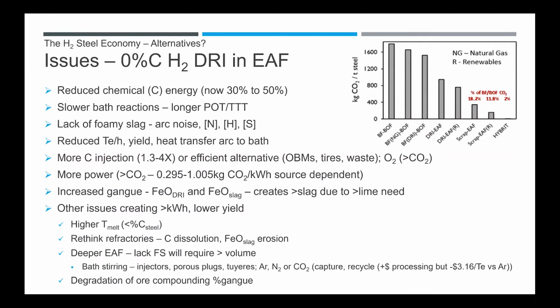What are they? Basically, they're going to reduce chemical energy, which is now 30 to 50%. We need to find some possible replacements. You're going to have slower bath reactions. You're going to have lack of foamy slag, which has its own issues, reduced productivity, yield, and heat transfer in the bath. And you're going to need more carbon in, whether it's injected or we have an efficient OBM situation or base metallics, or we can use tire wastes or other materials, but it's going to require more oxygen, which is more CO2 and more power.